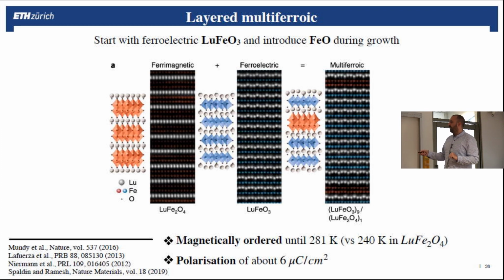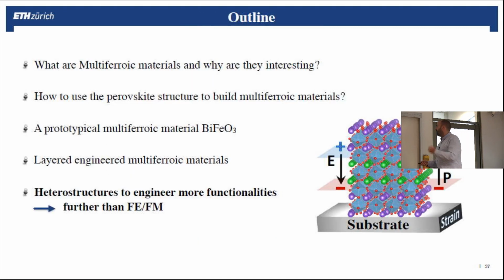And by doing so, you see that you have here your ferrimagnetic system, here the ferroelectric system, and by combining them together in that way, so that means 9 unit cells of this one for 1 unit cell of that one, you get this material where you can see that you have here these distortions, and these distortions are responsible of the polarization or the ferroelectricity in your material. And for this particular system, they observed that it was indeed magnetically ordered, so ferromagnetic, and it has also a polarization, small value, but still it's a proof of concept that you can engineer multiferroics by also this technique.